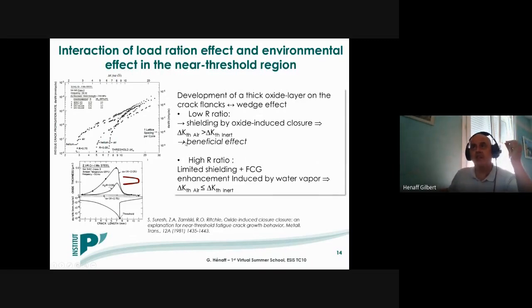But what is important to note is that this is beneficial from the point of view of the global fatigue crack growth resistance. However, at high load ratios, the shielding induced by closure will be extremely limited. And in addition to that, as you can see here, this is partly due to the fact that the oxide layer will be much thinner in that case. So you will have a combination of a limited shielding by crack closure, but still the presence of the fatigue crack growth enhancement by water vapor. And as a consequence, the threshold in air will be lower than the threshold in inert environments.